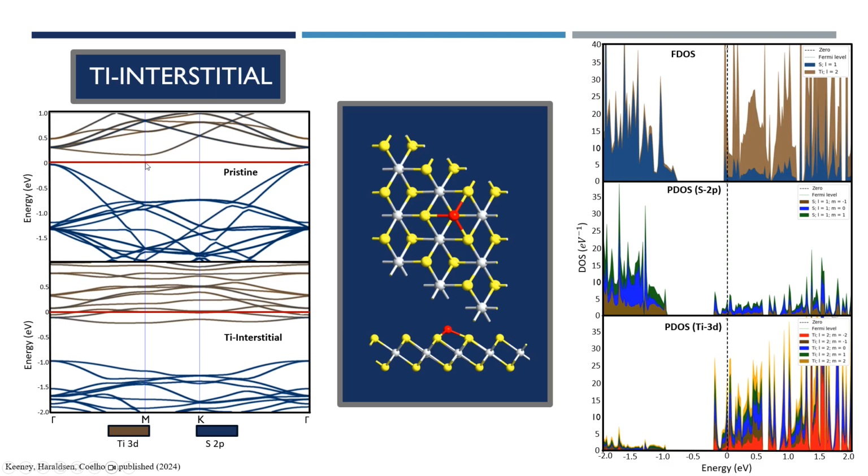And what you find is that the Fermi level, which is defined as the highest energetic state of any occupied electron within the system, rather than being in this little vacuum of space where there are no bands present, actually shifts up into the conduction band and will settle right in there with all these titanium 3D bands. And what this indicates is that the system is shifting from a semiconductor into a metallic system, given that you then have this highest energy electron that is occupied already within this conduction band and the conductive region.